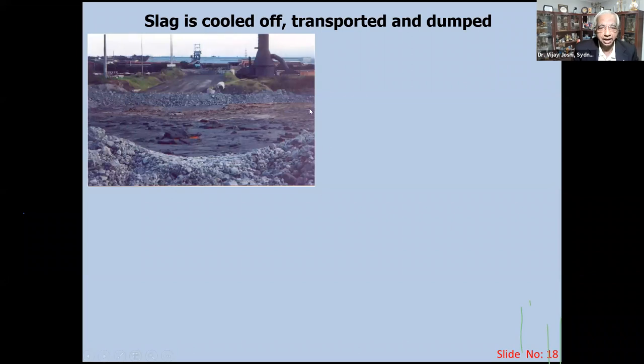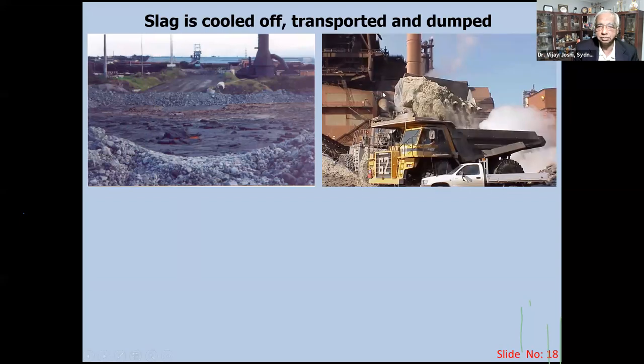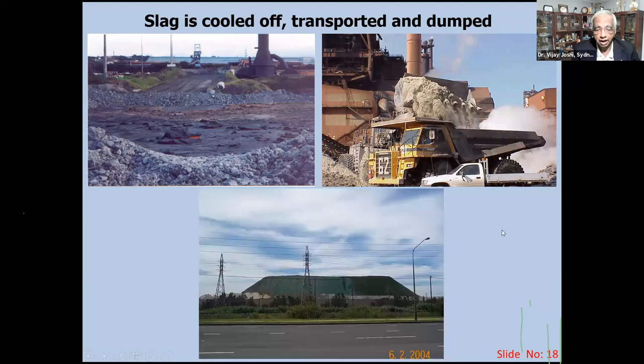You can see that it's being air-cooled in the pit, a dumping pit. Normally, from 1400 degrees centigrade to 100 degrees, which is a transportable temperature, it takes about 48 to 72 hours. So after this air cooling, big loaders pick it up, and you have the big mining trucks, which are 50 ton. In fact, in Australia we have about 100 ton trucks, because they travel internally within the steel plant. And once the truck goes, you can see the big mountains being formed.